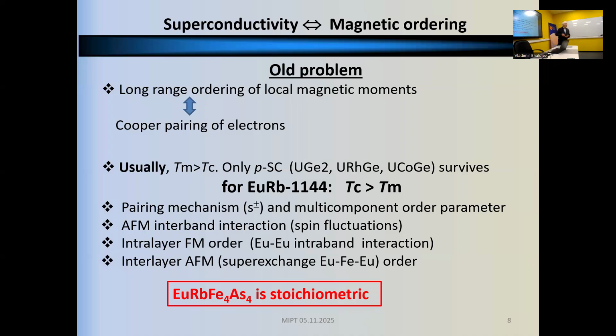promote magnetic ordering of the europium atoms, because they are located quite far away, about 13 angstrom from each other, and therefore direct dipole magnetic order is ineffective. So we thought this is a puzzle. In fact, there is no puzzle. But we understood this 4 years later just by putting some numbers on the various kinds of interaction. But at the beginning we decided to study this experimentally, and it was quite